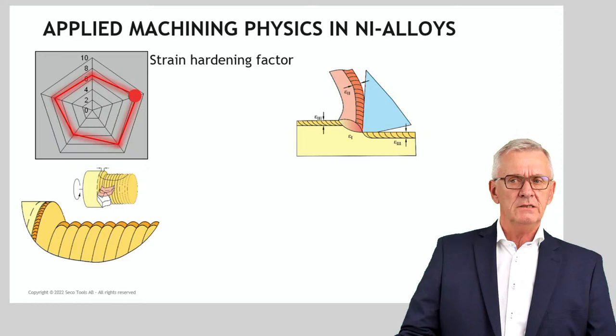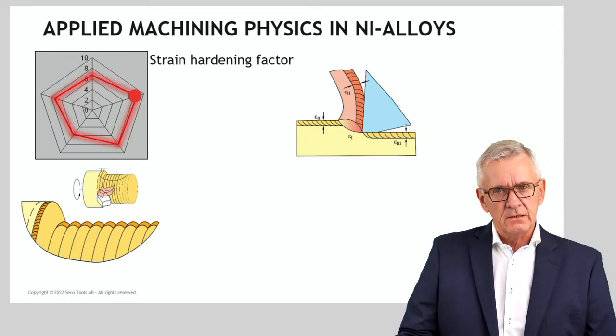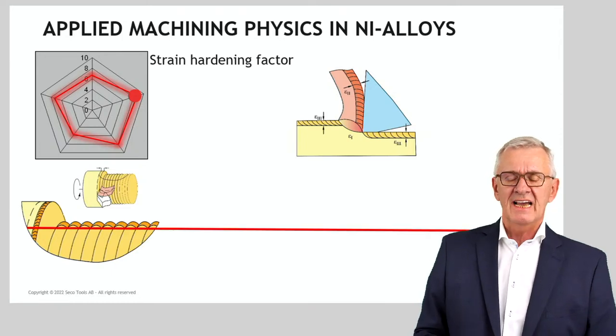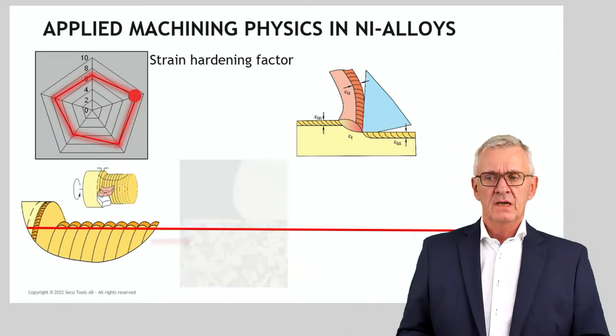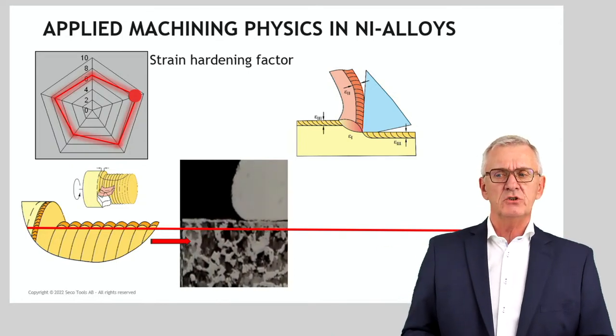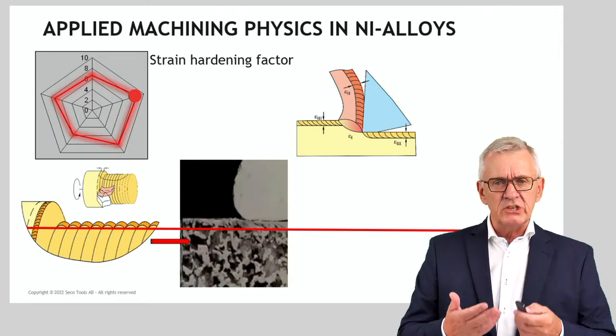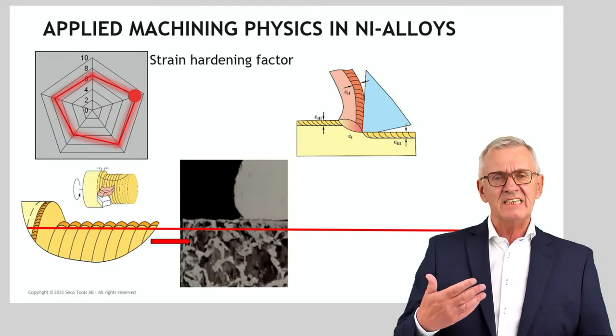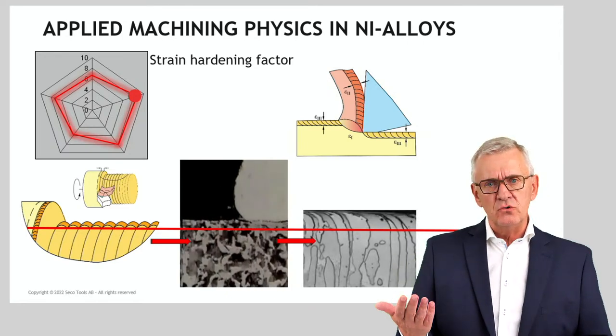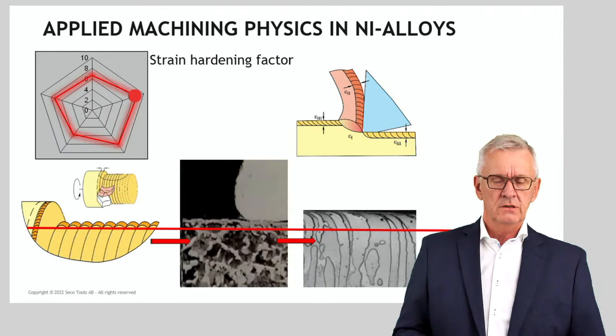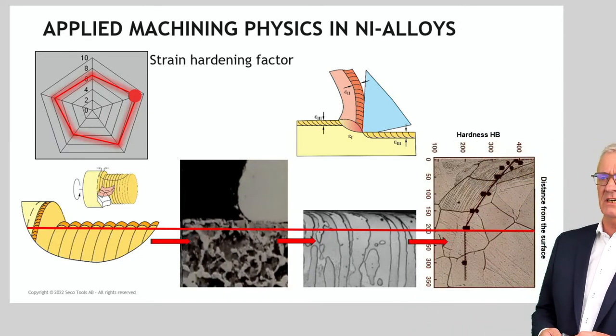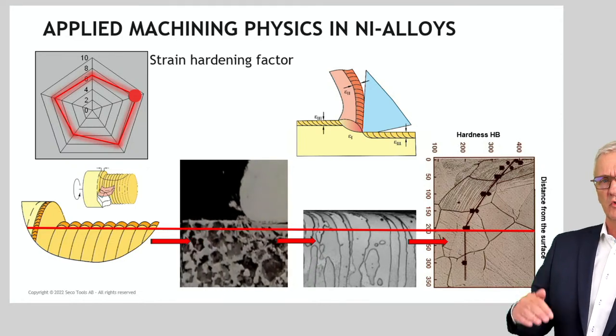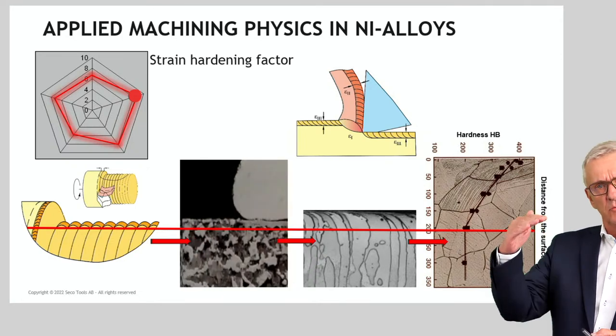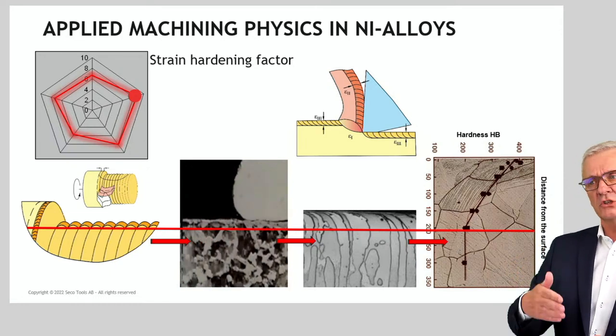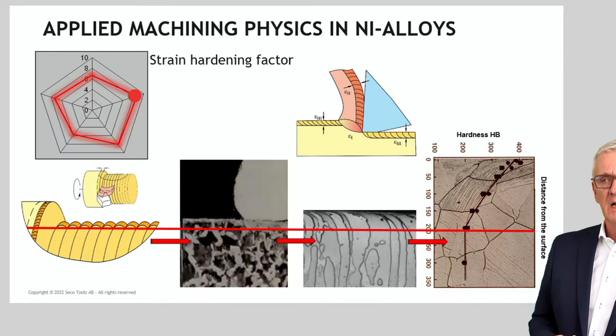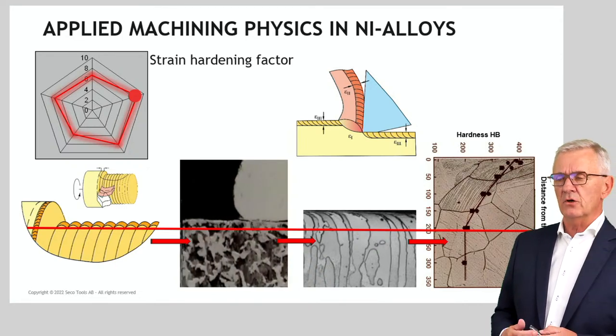So if we do machining, we could unintentionally create strain hardening in the machined surface. And that means that if you look after machining, that the surface, and the video animation gives you an idea here, I hope, of that deformation taking place just below the cutting edge. Well, that deformation of workpiece material leads to a strain-hardened surface that is noticeably harder. The last graph to the right shows you, from top to bottom, top is on the surface, and if you move down to the bottom, you move into the material structure, and the horizontal axis here gives you the hardness, the micro-hardness, and what you see is that after strain hardening, the micro-hardness went up.